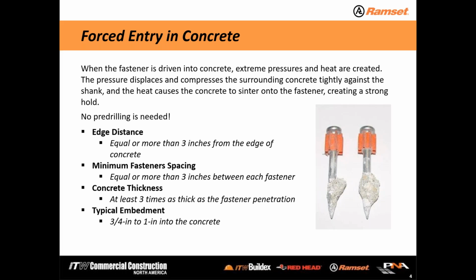Fastener spacing, again, here is about 3 inches. So you don't want to disturb the localized bond that's created from the driving mechanism there, and that spall cone that you see there in the photo. So concrete thickness, again, another number 3: 3 times as thick as the fastener penetration.